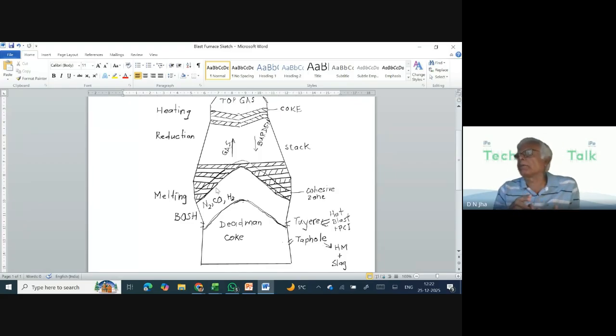So the first phenomenon that we have seen is the heat transfer that is taking place within the blast furnace. And what is the source of the heat? The source of the heat is the carbon oxidation in front of the tuyere. Carbon oxidation means what? C is getting oxidized to carbon monoxide, and in the process, every kg of carbon, once it gets oxidized to CO, generates a heat of 2450 kilocalorie per kg of carbon. So that is what gives the heat.